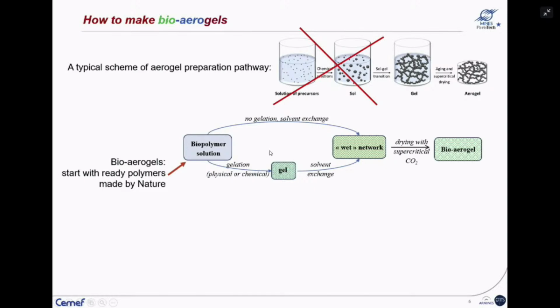It has to be said that acetone or ethanol are not solvents for the majority, or at least for native polysaccharides. So here, as a precursor, we don't have a gel, but we have a sort of a wet network of coagulated polymer. But the magic point of polysaccharides is that the polymer is not completely collapsing as many synthetic polymers. It is keeping the 3D structure, so it keeps the network morphology. It can shrink a bit, more or less, but it still keeps a 3D dimension.